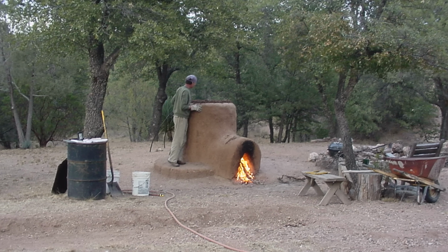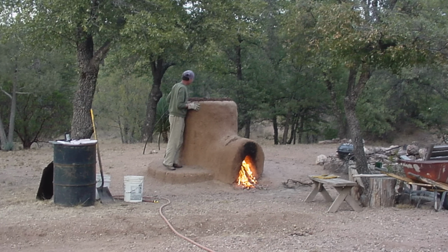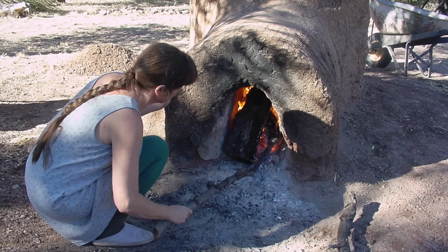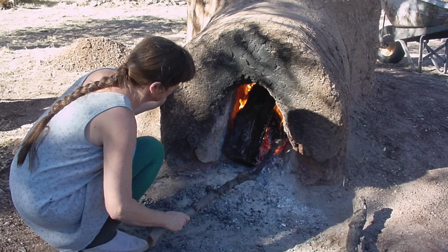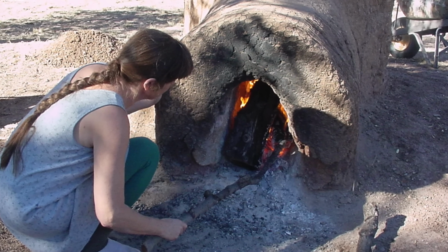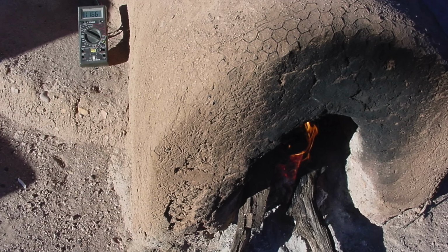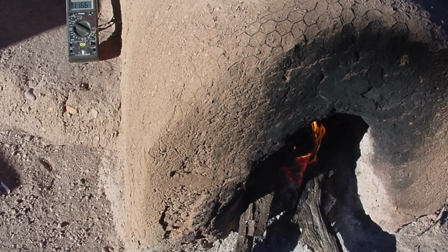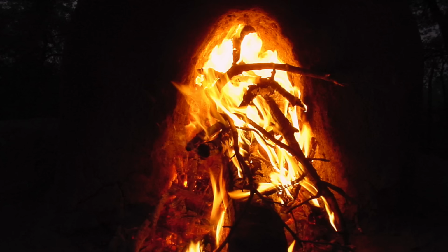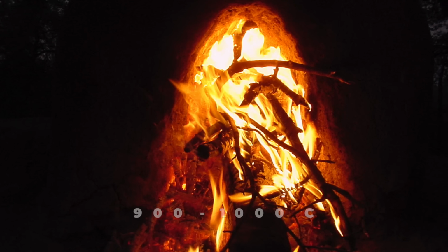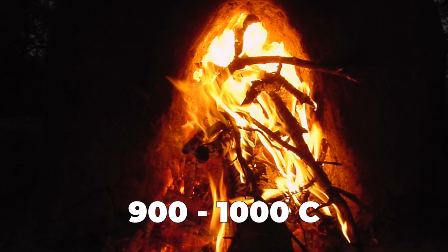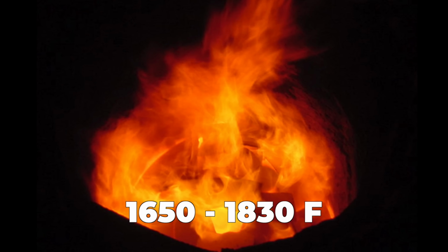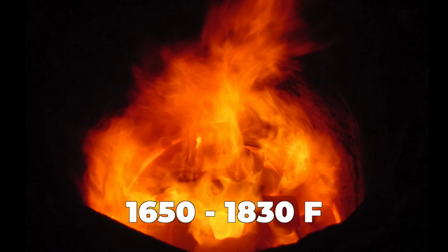For most of the time they were using this kiln, the Thornburgs did not measure the temperature except what they could read by using the corn kernels and the soot level. But for a time, around 2004, they were using a thermocouple, so I can tell you that their firings generally reached between 900 and 1,000 degrees Celsius. That's between 1650 and 1830 Fahrenheit.